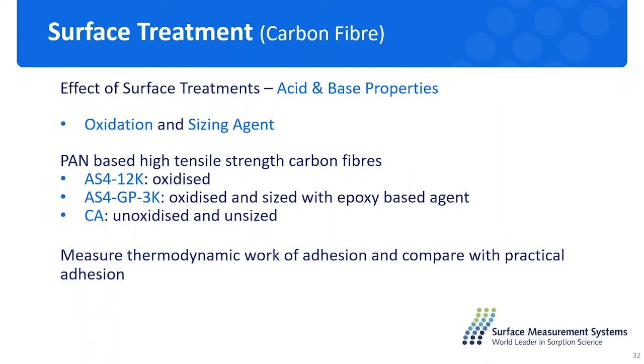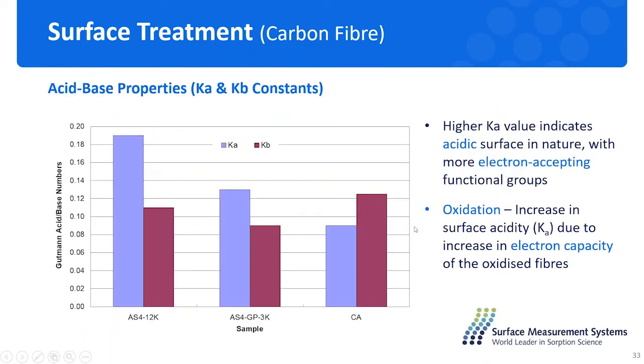We calculate the Ka-Kb value, acid-base property of this material. So basically here we have the Ka-Kb value from different kinds of polar solvents, and the as-received carbon fiber with the higher Kb value, which indicates more electron-donating groups on the surface, for a more basic nature of the original carbon fiber. And by the oxidization process for the first two carbon fibers, the Ka value increased a lot. That means we introduce quite a lot of electron-accepting functional groups on the surface.